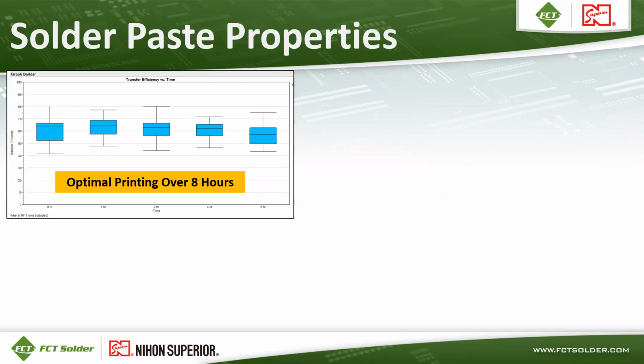Now, I'm talking specifically here about one of our solder pastes. In this case, we tested it for printing over an 8-hour time period with print and pauses. What you're looking at is a chart of transfer efficiency initially on the left at time 0, and then after 1 hour, 2 hours, 4 hours, and 8 hours on the printer. You can see the transfer efficiency data is fairly stable over 8 hours on the printer with long pauses.